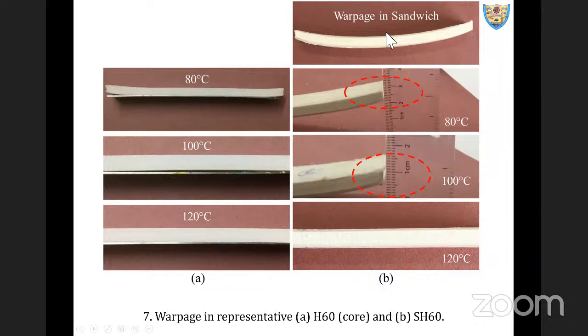Okay, this is what you see. While printing, it perfectly prints. And after printing, as we leave the sample onto the bed to cool, the complete sandwich bends like this. You can see there is no interface failure. We did not observe any, neither by naked eye, between the skin and core and the skin subsequently.